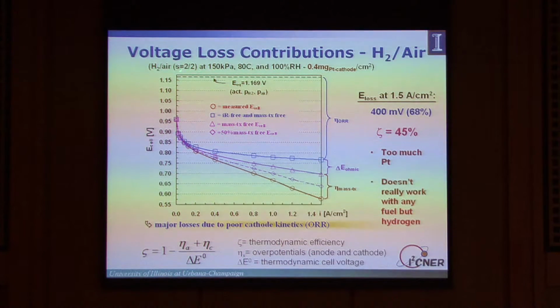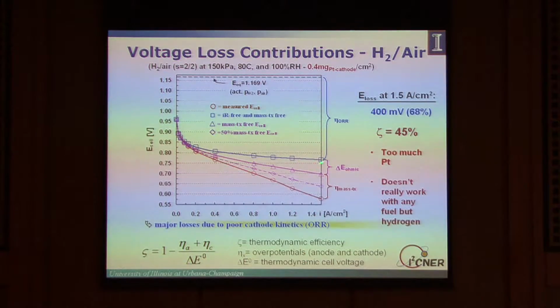What you can see is that even before you start passing any current at all, you don't develop that 1.2 volts. You actually develop about 300 millivolts less. And then as you start passing current, and people think that realistic amounts of current are around 1.5 amps per square centimeter of electrode area, you can see that the cell voltage drops considerably till it's less than half of what the thermodynamic value is. Now we can analyze what the cause of this drop is, and it turns out something like 2/3 of that drop just comes from the slow kinetics of the oxygen reduction reaction. In other words, cleaving that oxygen-oxygen bond, doing that chemistry, is very difficult in a PEM fuel cell. I'm not talking about a solid oxide fuel cell, where of course there's a different type of chemistry going on entirely.